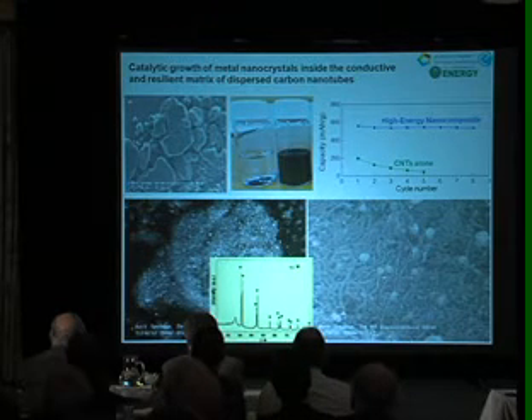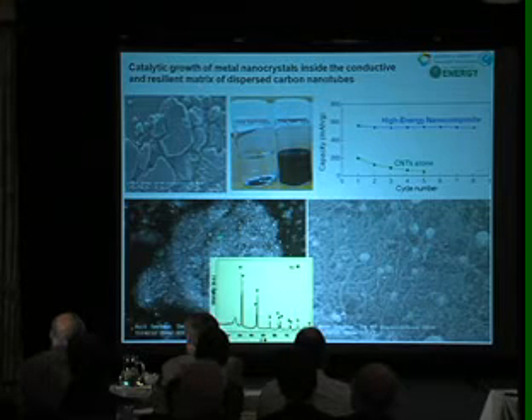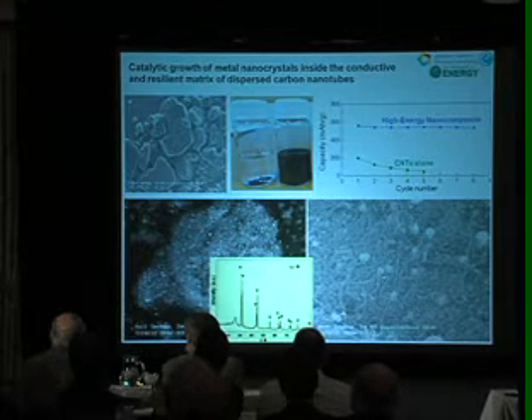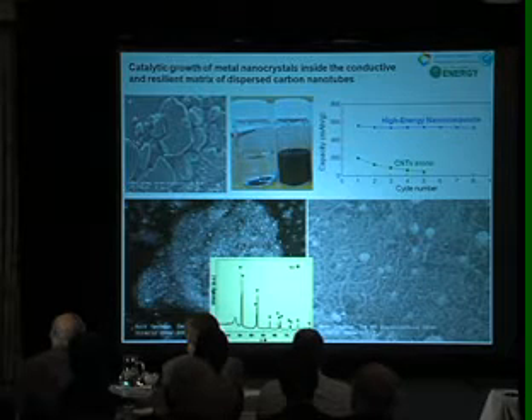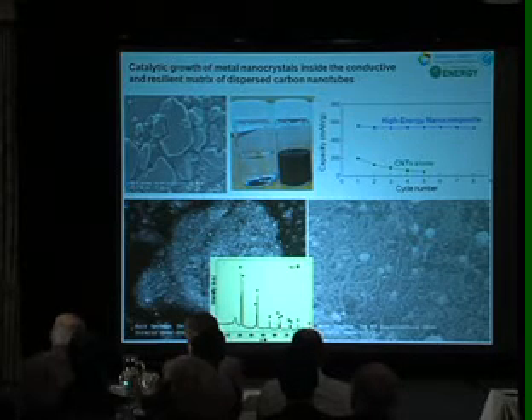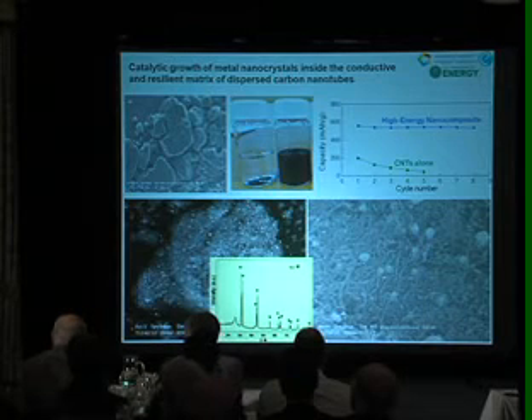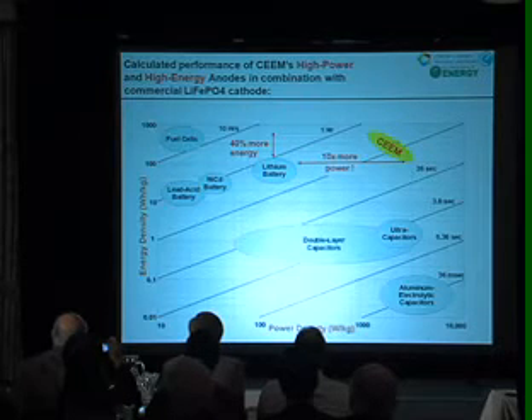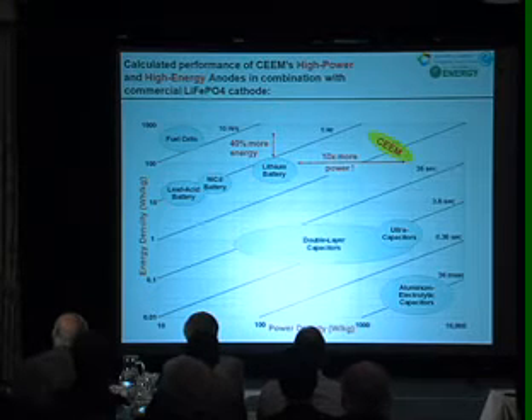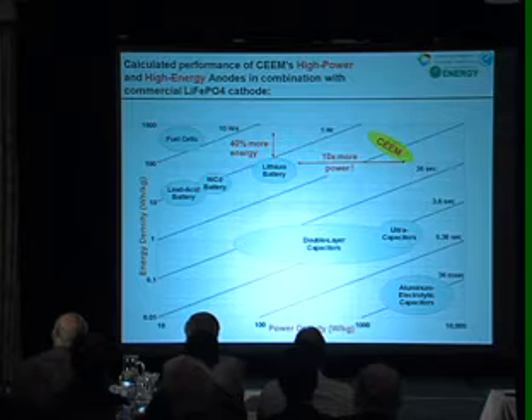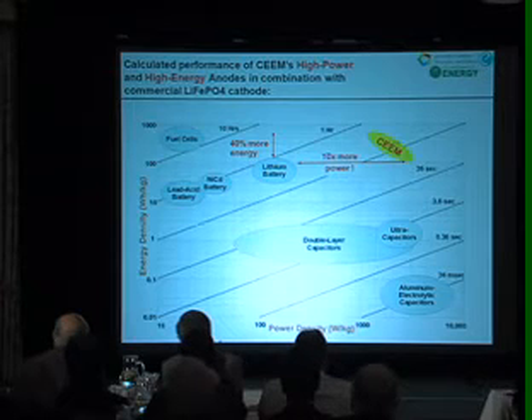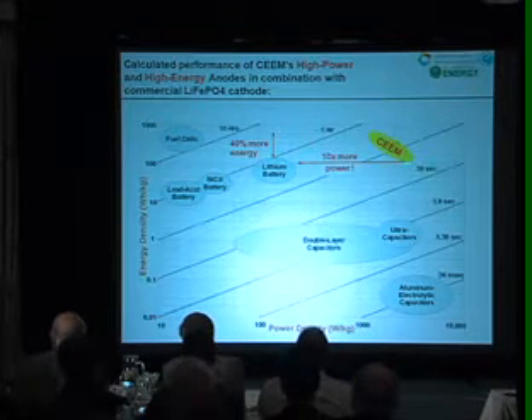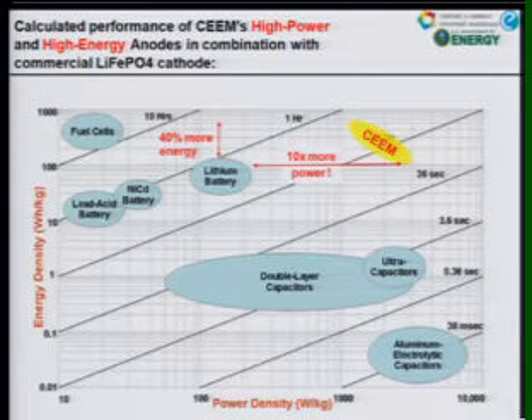This is an X-ray diffraction analysis of the nanocomposite, just confirming that all of the tin oxide that we've produced in the first step is subsequently reduced to nanocrystalline tin. Highly pure. If we calculate the expected performance of these high-performance anodes in combination with the conventional lithium iron phosphate cathode, we see that these anodes offer 10 times more power than present conventional and commercial lithium-ion batteries, and about a 40% higher energy density.